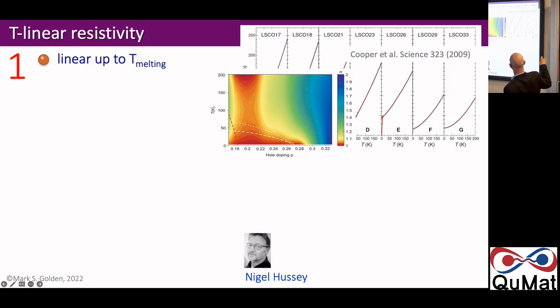So if you look at the power of the resistivity as a function of temperature, of course, transport people have a very powerful experiment, and the only knob they have is temperature. I'll be showing you later that we can change both frequency and temperature in an ARPES experiment, but we're not as highly resolved as the transport people are. But if you look at rho goes as T to some power n, this is 2 way up here, way beyond the superconductivity, and it's strictly 1 around the optimal superconducting temperature. So this is the superconducting dome sketched in. This is the superconducting fluctuation sketched in. So here it's really linear all the way up to very high temperature. But if you suppress the superconductivity with a high magnetic field, you see that there are linear components at low temperature all the way across.